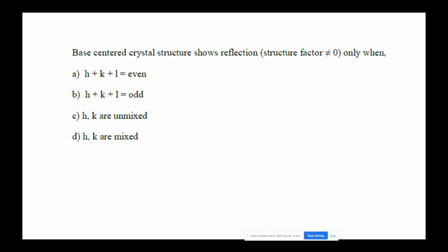Now the body center crystal shows reflection only when H plus K plus L is even. So H plus K plus L is even, sir. Yes, just before you said that for the forbidden it is odd, and the structure factor is not equal to 0 when H plus K plus L is even.